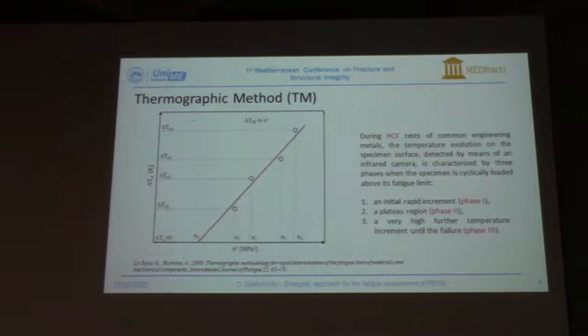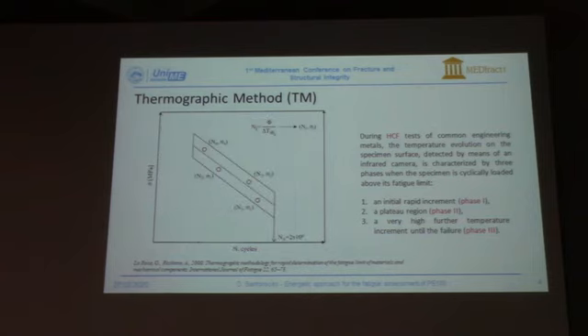So we can plot the stabilization temperature versus the stress level, and we can estimate the fatigue limit as the intersection with the stress axis. In addition, we can obtain the Wöhler curve for the material.